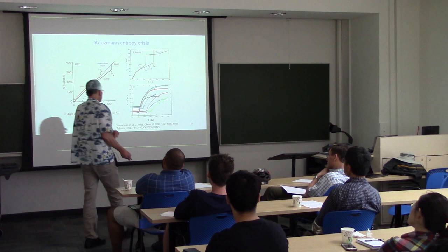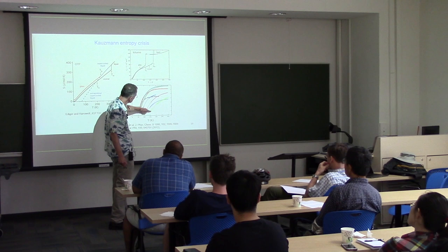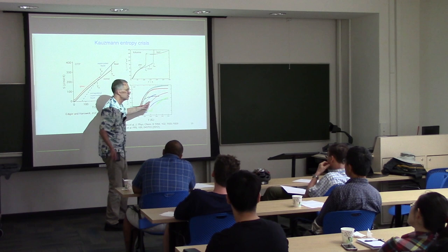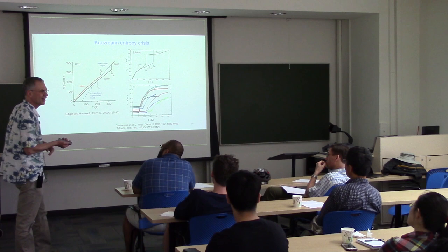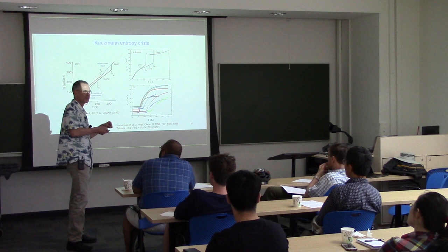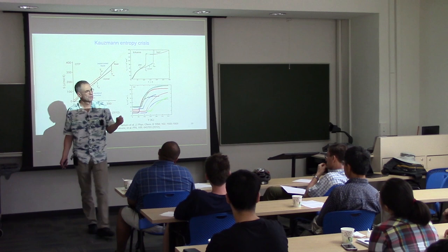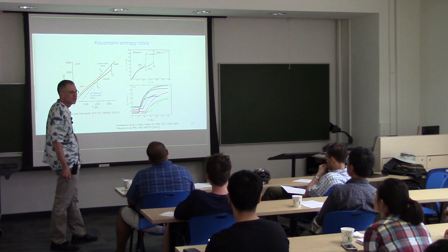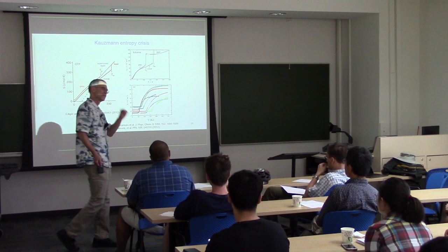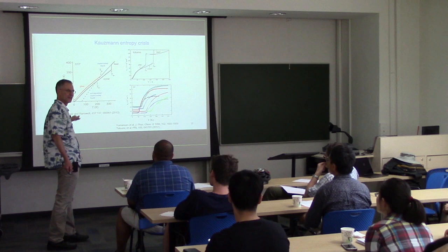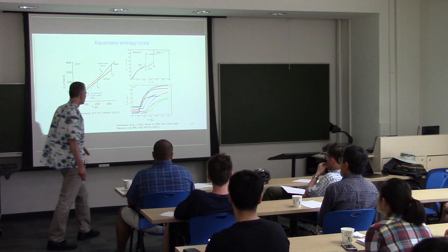Of course, if you can come up with a theory that says that if I stayed in equilibrium, I would stay on this line, but then it would curve off, and of course, the extrapolation has to be wrong. We believe the extrapolation is wrong. So the interesting question is not, is the extrapolation wrong? The interesting question is, how do we get rescued from that result? Okay, and some sort of a phase transition that happens when the configurational entropy gets to zero is just one possibility. And a smooth gradual curve would be another possibility. There could be a phase transition before the configurational entropy. I mean, there's many possibilities. But the point is that in that first plot I showed you, you can't just keep going down that line forever. There is a real limit on the kind of amorphous structures that can be prepared. And the configurational entropy is going to have to stay above zero.